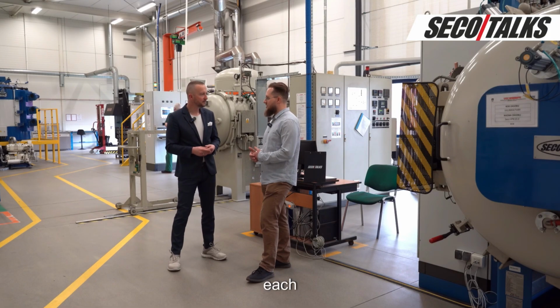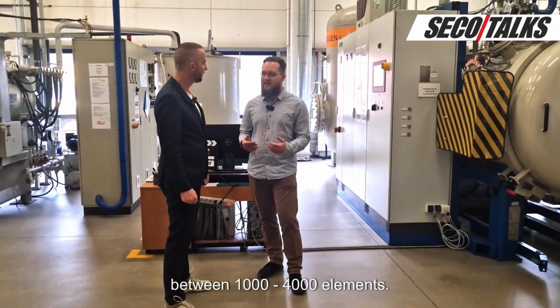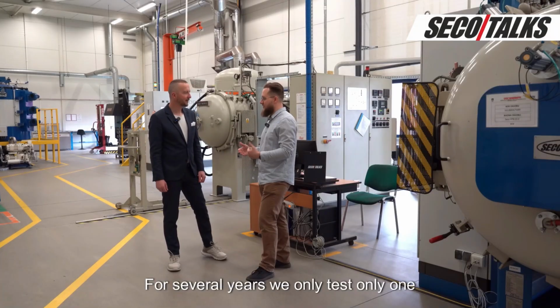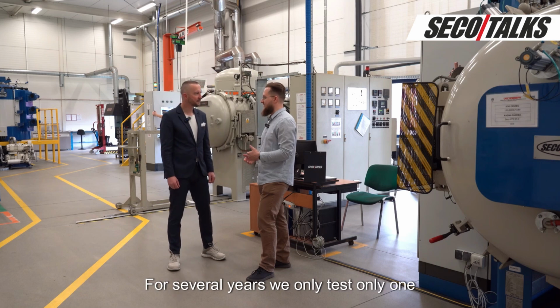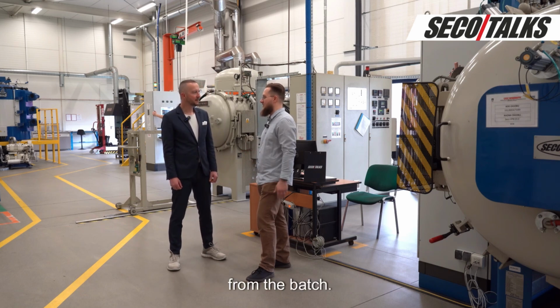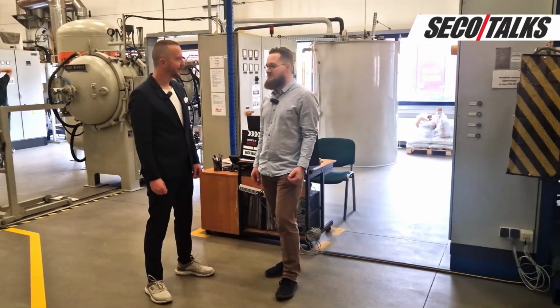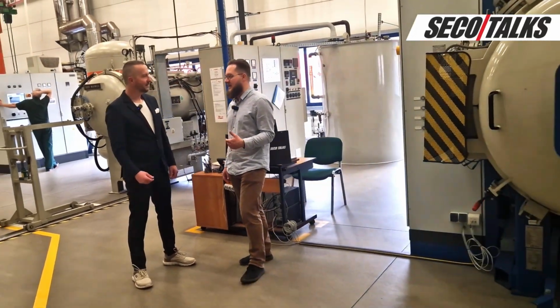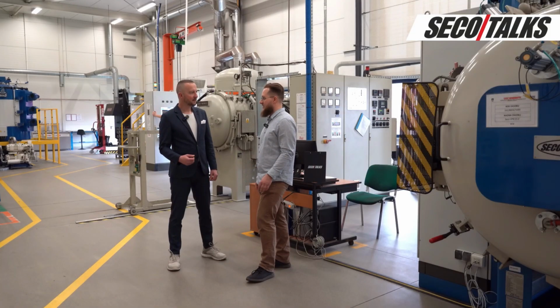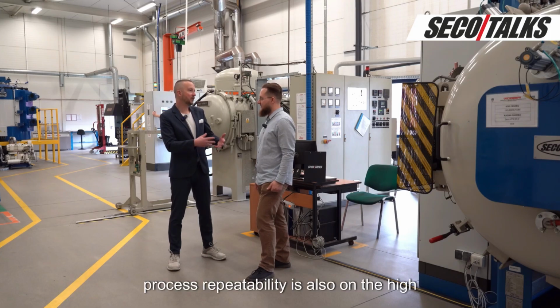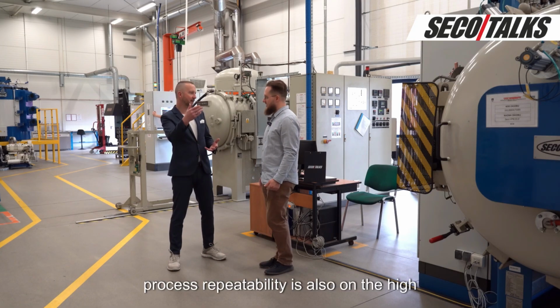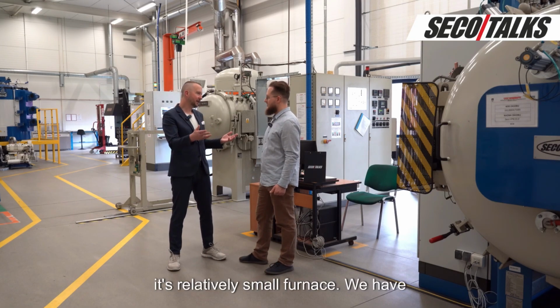Well, in each heat treatment batch, carburizing batch, we have between 1 and 4,000 elements. For several years, we only test one element from the batch, chosen randomly. And we haven't noticed any differences. So it means that the process repeatability is also on a high level. I understand. It's a relatively small furnace.